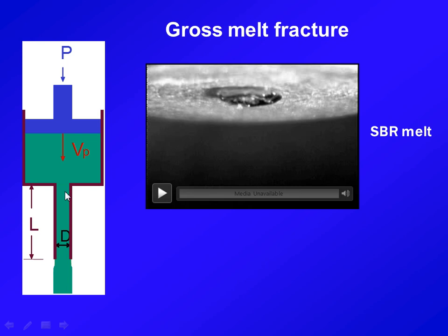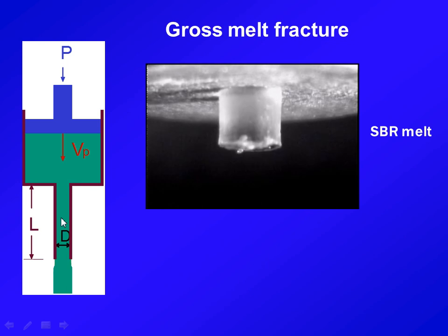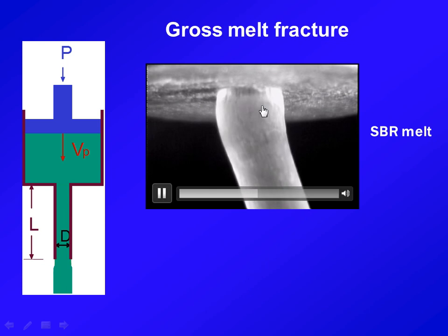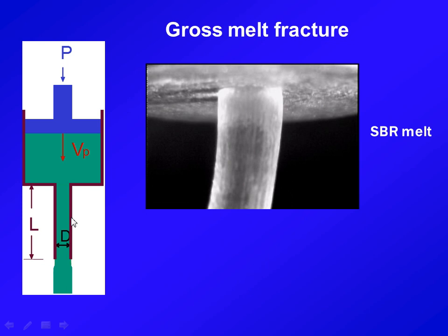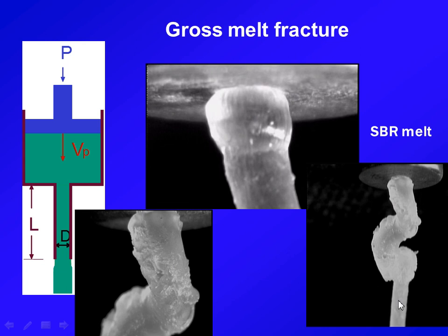So remember, the sample that's already in the die is relaxed, already forgot it went through the entry. And this part that's initially being extruded out comes out smoothly, beautifully, because it didn't undergo that. It was sitting there resting already. Now what's coming out is the material that's constantly being fed in. And so that's the smooth part. The rest is distorted because the residence time is so short. The sample still remembers the nasty history it went through at the entry.